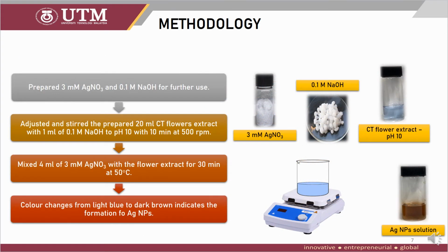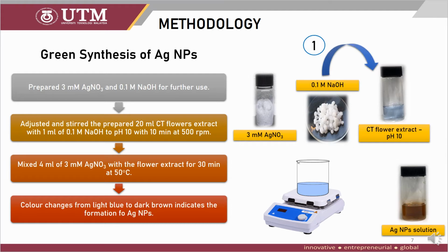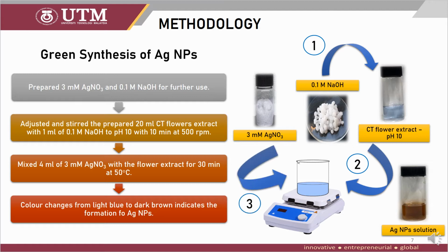So next is the methodology for the green synthesis of silver nanoparticles. First thing first is to prepare 3 millimolar silver nitrate and 0.1 molar NaOH for further use. After that, the 0.1 molar NaOH will adjust the pH of the flower extract prepared before to pH 10 for about 10 minutes. After that, this mixture of flower extract with NaOH will be mixed with 3 millimolar silver nitrate solution to get the silver nanoparticles. And during this mixing, the color changes from light blue to dark brown, which indicates the formation of silver nanoparticles.